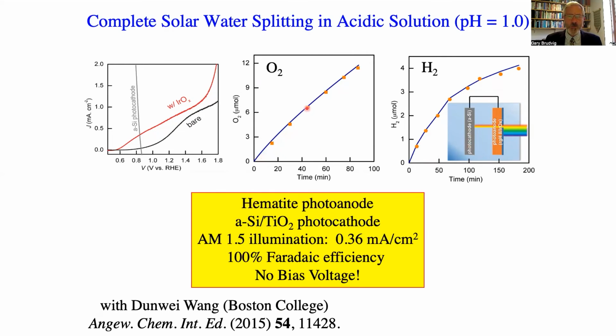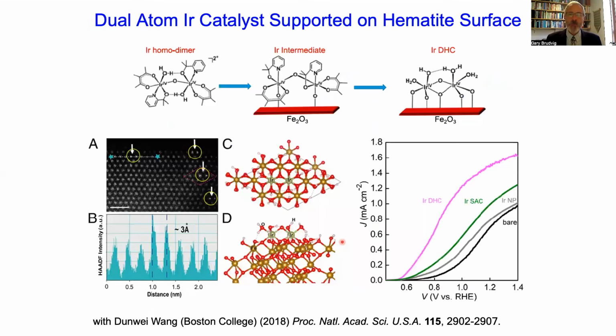And you can see the measured hydrogen and oxygen, which occurs with essentially 100% Faradaic efficiency with no bias voltage. So this is something that demonstrates the potential for these molecular catalysts. We've also examined not only the catalytic performance, but also the structure on the surface. So this again shows the photocurrent as a function of applied voltage.